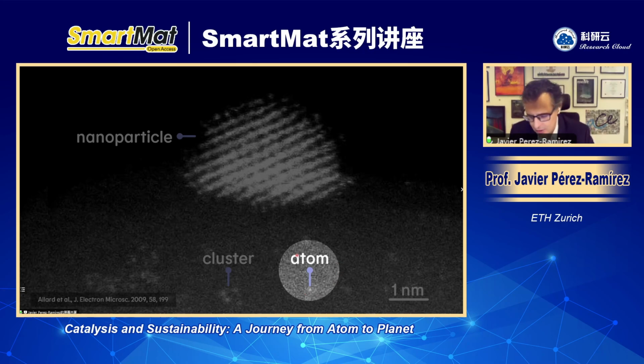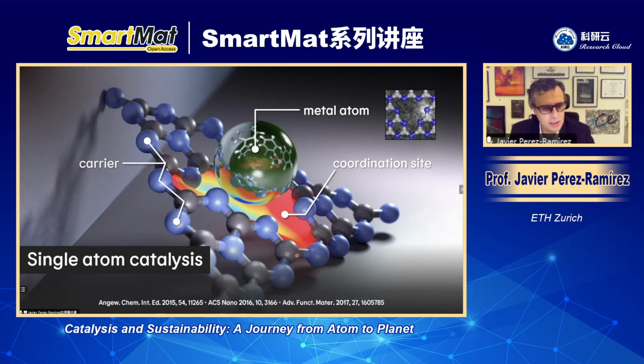So the structure of a typical single atom is illustrated here. I used this slide to introduce what single atom catalysis is. Single atom catalysis is essentially heterogeneous catalysis with a metal atom that is stabilized in a solid scaffold, in a solid carrier, sometimes called host, in a coordination site of the host so that the metal atom is stable. As you can see in this real-time microscopy sequence, that single atom, in this case I think is palladium, is stable in the cavity of this host, of this carrier. And this particular carrier in this slide is carbon nitride, graphitic carbon nitride.